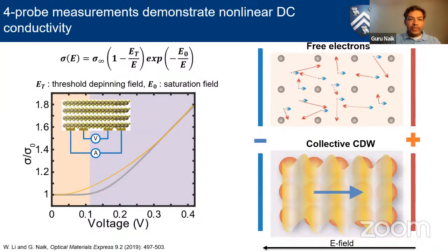So what we did, in fact, is, as I mentioned, exfoliate a thin film, 20 to 80 nanometers. So we have different thickness samples, just that crystalline film, and then put it on a substrate and then measure optical properties. Even before we did optical properties, we measured electrical properties, just to prove to ourselves that there is this charge density wave behavior. A typical way to prove that is to show that there is a nonlinear DC conductivity in this material, and that has a particular form, which in fact comes from the theory of how these charge density waves can be trapped in defects, and you have unpinning of these charge density waves at a threshold electric field called ET. So we see a very similar behavior as theory predicts, which is an indirect proof that charge density waves exist at room temperature in this material.